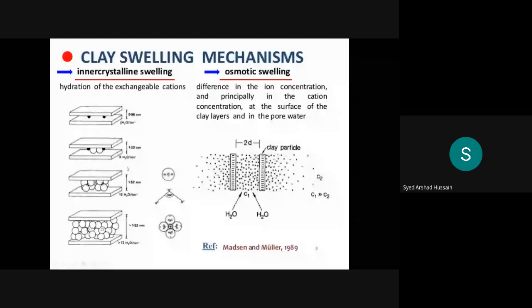The main mechanism underlying this swelling is maybe hydration. This is one issue, and then another is the pressure difference between the clay layers and the outside environment, that is, the solvent. And due to these two differences in pressure, osmotic swelling occurs. That is, solvent from outside enters in between the clay space and the sheets or layers separate from each other and swell even up to single sheets.